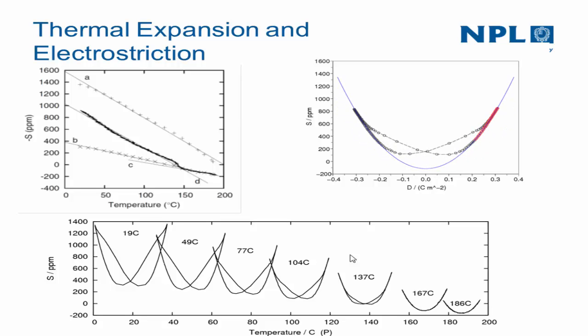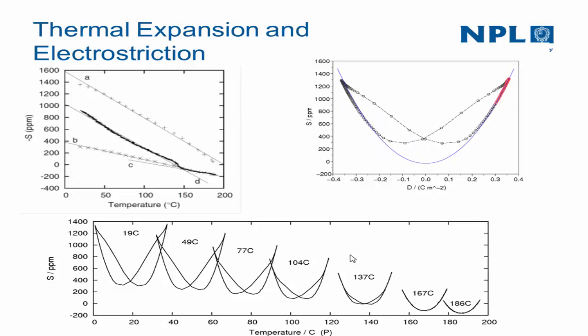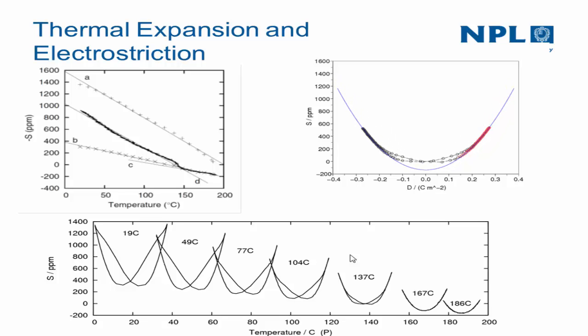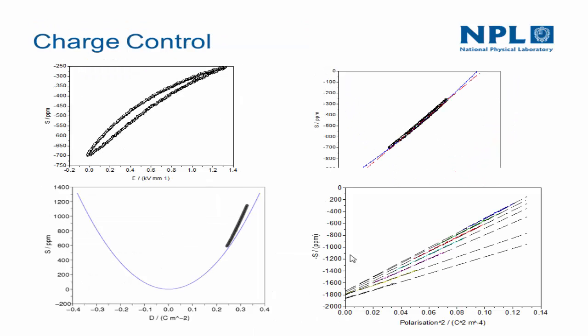So this little movie here, you can see this part of the curve is fitted to a parabola, which would be descriptive of electrostriction. This is the ferroelectric regime, and then above the Curie temperature it collapses all onto a parabola. So we can use that to describe a lot of the thermal expansion and piezoelectric expansion in these materials.